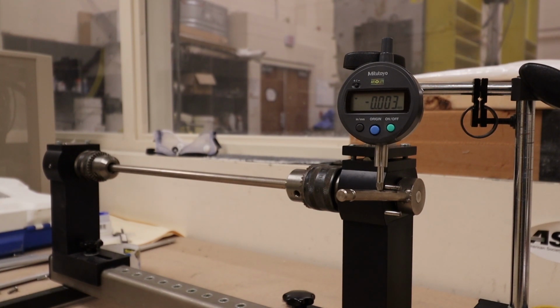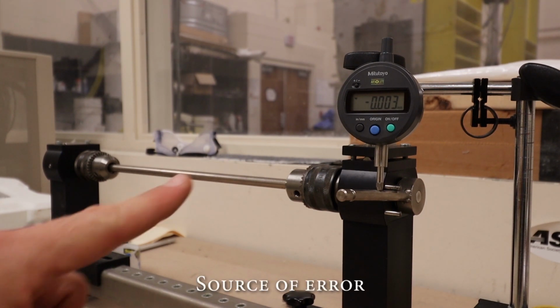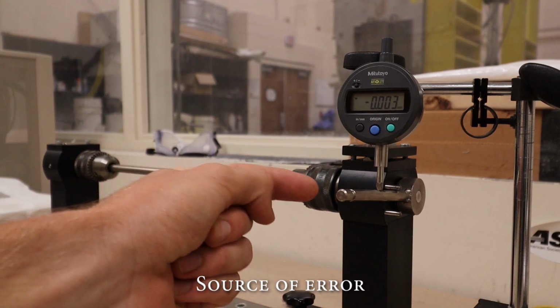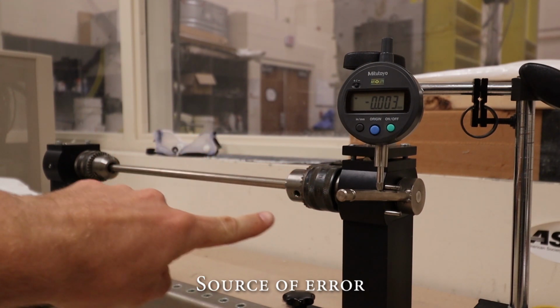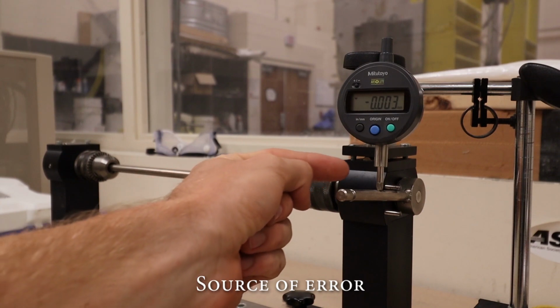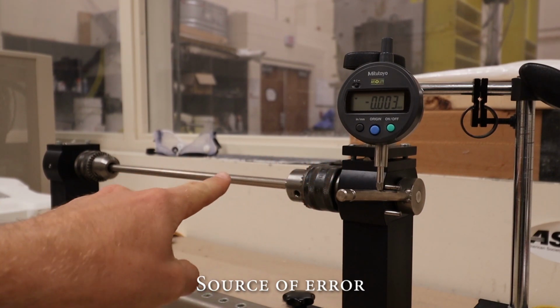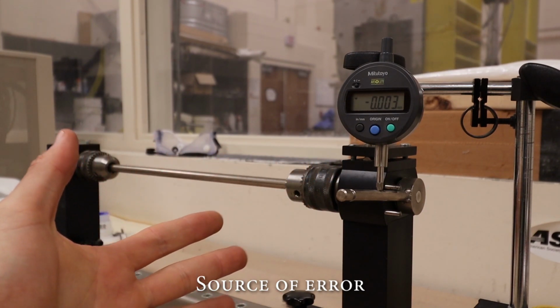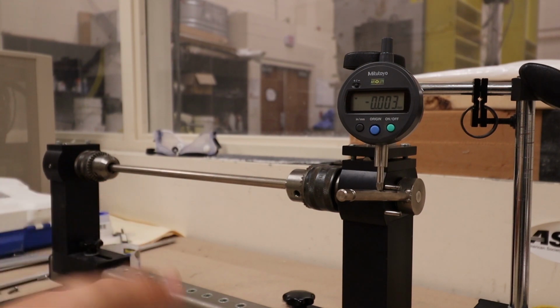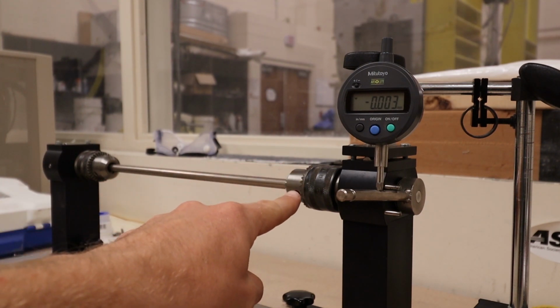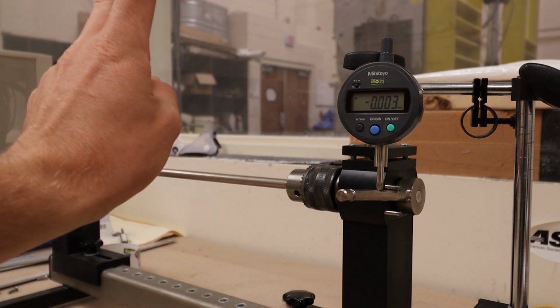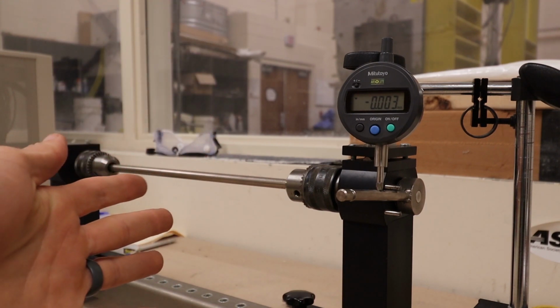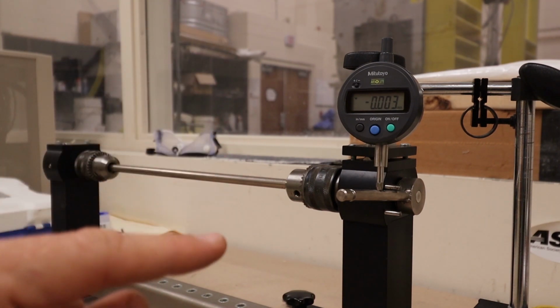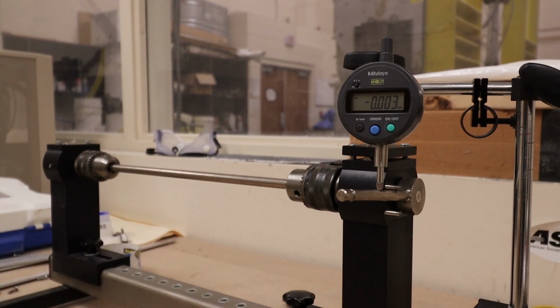The big thing that we're going to assume here is that all of the loading that is occurring right here is being transmitted into our rod. We're not losing any mechanical energy through this whole setup, which of course is not going to be the case. With these drills, the drill bit is not 100% welded and attached to the steel rod, so it's not going to be transferring all of the energy. So account for that and make sure you mention that in our lab report.